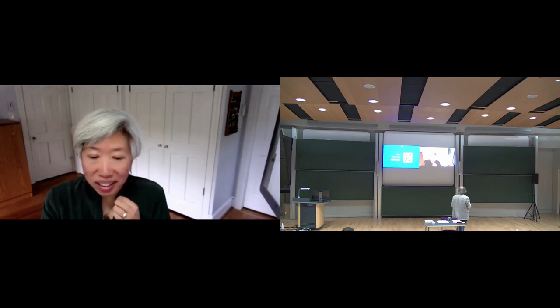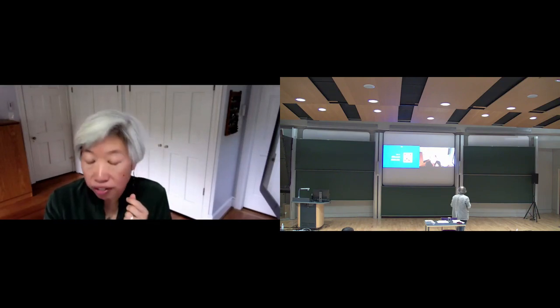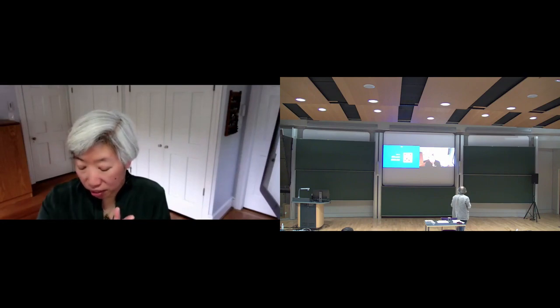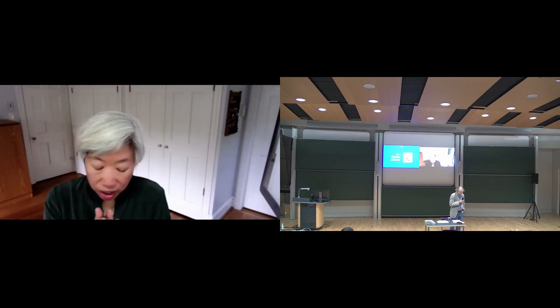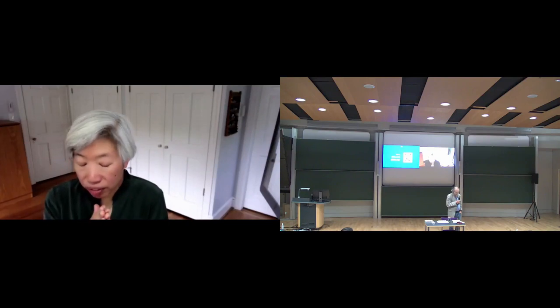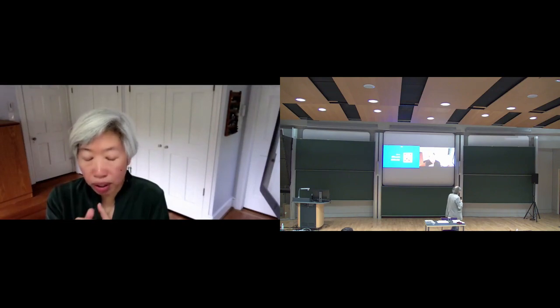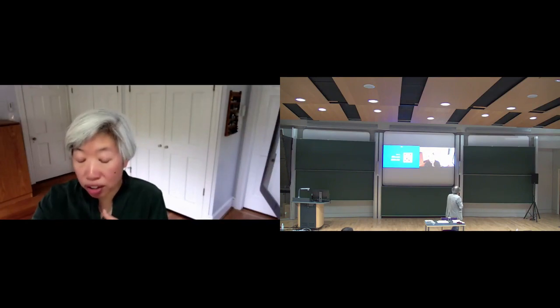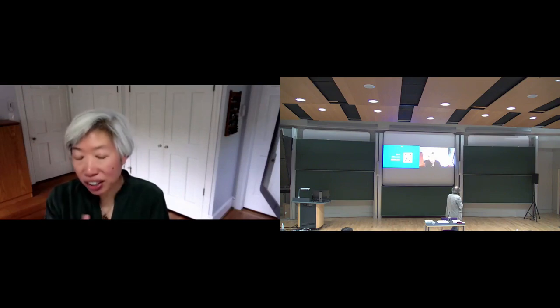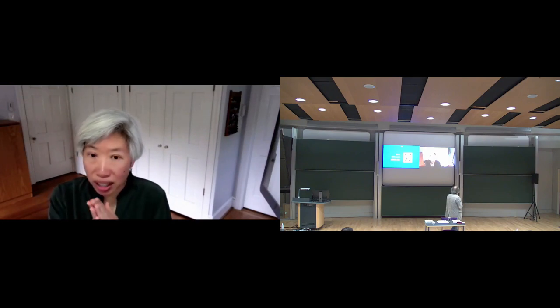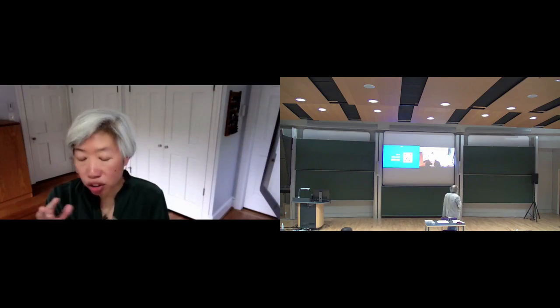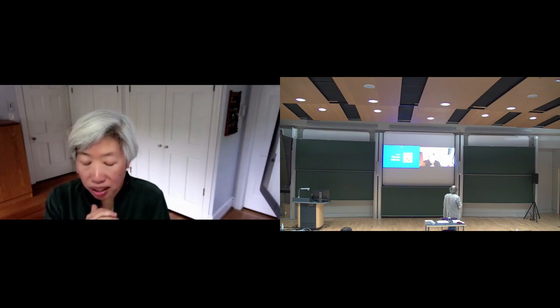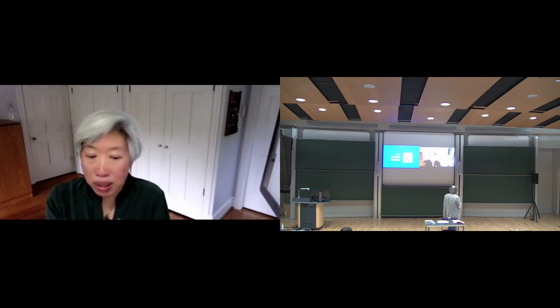And for interesting reasons. It turns out that, for example, we tried to apply softness to thin films, to the glassy dynamics in thin films. And near an interface with vapor or nothing, which is what you have inside a crack, what we find is that softness, it's been well known in thin films that the dynamics speed up near the free surface. Softness utterly fails to predict that. In fact, there's no change of structure of any kind we found with machine learning as you go to the edge of the film until you're very, very close to the edge. And yet there's quite a bit of speed up of the dynamics, even further into the system where there's no change of structure. And it turns out that that's from a piece in the probability of rearranging which does not depend on structure.